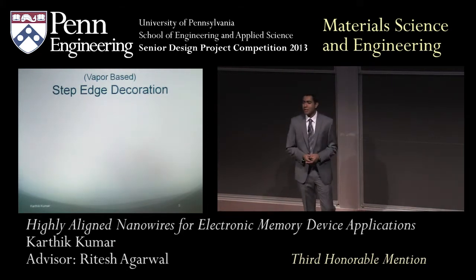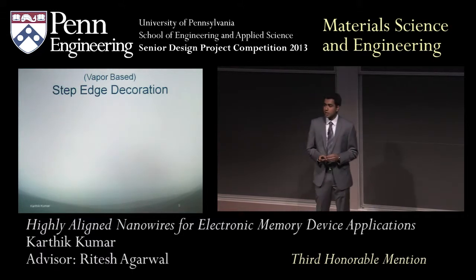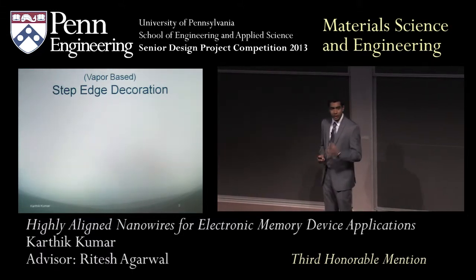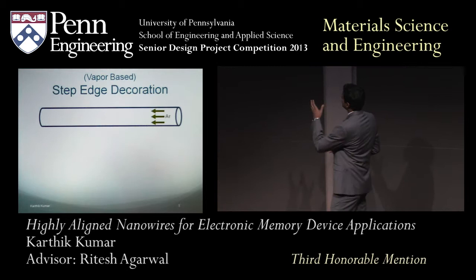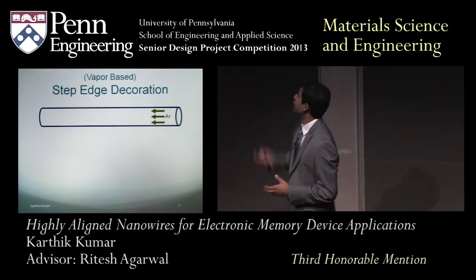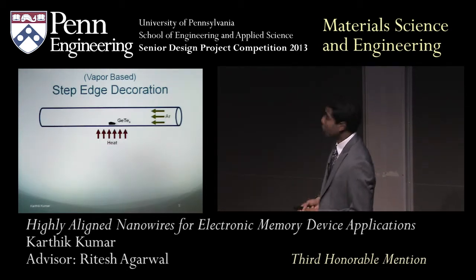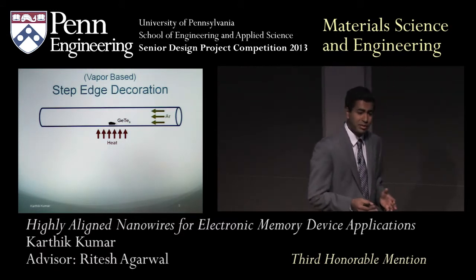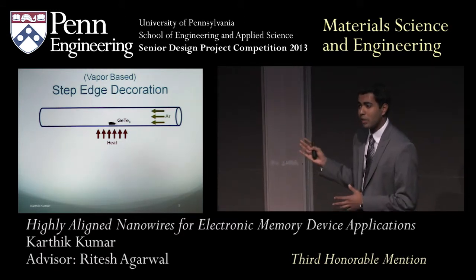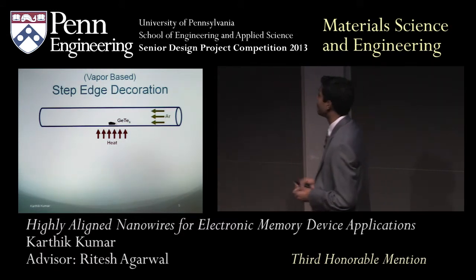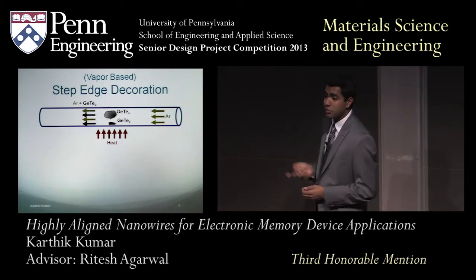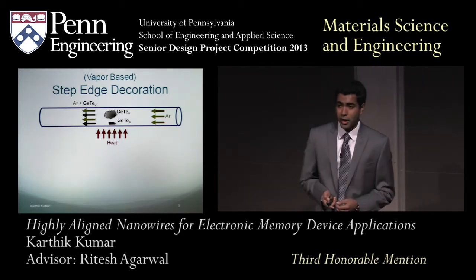Enter my proposed vapor-based step-edge decoration. This draws inspiration from past work on electrochemical step-edge decoration, which takes place in solution. In my method, however, we start off with a quartz tube with an inert argon flow. We then put our precursor in the middle of this tube, in this case germanium telluride, phase change material. When we heat it, it forms a vapor which is carried to the downstream end.